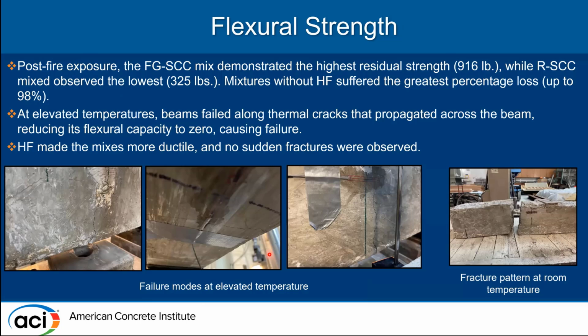I'm trying to explain the failure patterns before fire exposure and after fire exposure. The image here basically shows the brittle failure that occurred for all the mixes before fire exposure, and the beam cracked at the midsection. However, these three images present a beam after fire exposure, where the failure occurred across the cracks that were developed during the fire exposure. The video I was trying to show you.